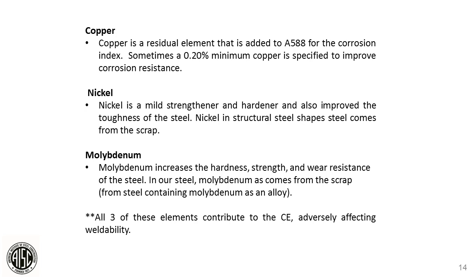Moly increases the hardness, strength, and wear resistance of our steel. And again, we don't add that intentionally in structural steel. It comes through as a residual from the alloys. And all these elements are contributors to the carbon equivalency formula that we discussed earlier. Next slide.